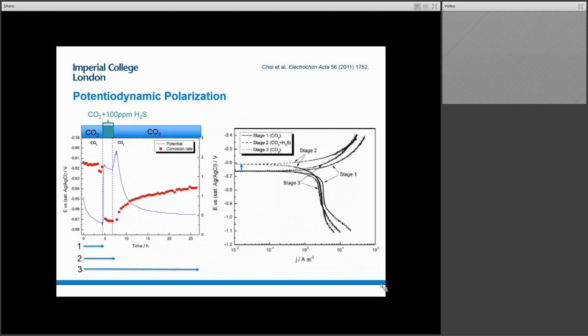The first thing that's quite clear to notice is that, so we have enumerated stage 1, stage 2, and stage 3, is that stage 2 looks different. And you can actually see that leap in the potential. That's not at all surprising, given what we have observed from the previous scan. So that's comforting, I suppose. But what the authors find particularly interesting, and as do I, is that the cathodic scan is not particularly affected by the formation of this layer. So stage 1 and stage 3 look quite similar. They're asserting that they've removed this layer, and so we're back to the same bare metal. So not so surprising, but the cathodic scan looking quite similar.